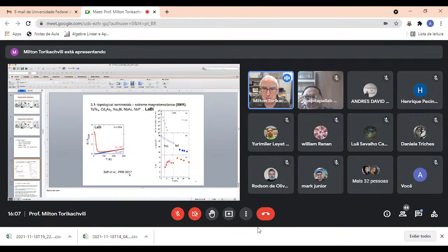So we performed a few experiments in pressure, and this is what we noticed. As we start applying pressure from 0 to 5 gigapascal, this magnetoresistance starts dropping very, very quickly, like at 3 gigapascal, it dropped by 3 to 4 orders of magnitude. And even more important, once the pressure got a little over 3 gigapascal, the material became superconducting. Once you got to 11 gigapascal, there was a crystallographic transformation from FCC to tetragonal. So this is obviously worth investigating.